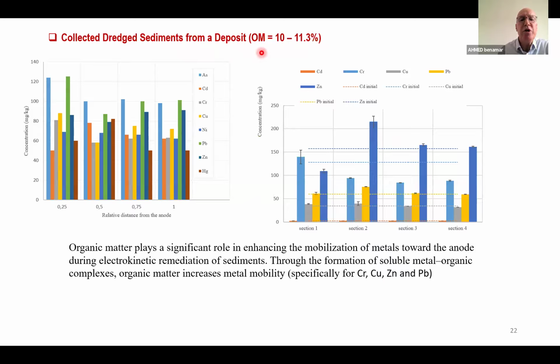But when we tested dredged sediments from a deposit, which have an organic matter content of 10 to 11%, we see that something happened: many metals can move. The cations can move to the anode instead of moving to the cathode. This disturbance is due to the relatively high content of organic matter. So organic matter can play a role in the electrokinetic remediation process.